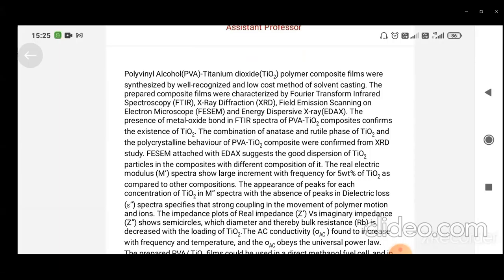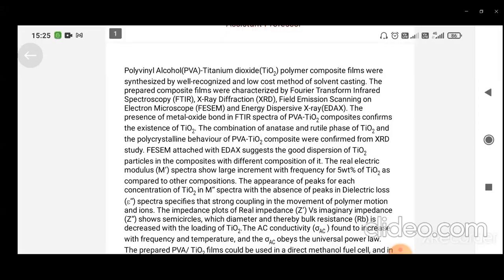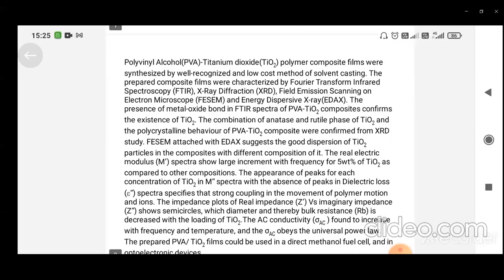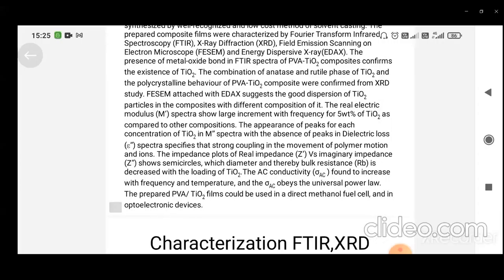TiO2 in polyvinyl alcohol. The polyvinyl alcohol TiO2 composite was synthesized using the solution casting method, also called the isothermal evaporation technique. To begin with, 1 gram of polyvinyl alcohol was added to double distilled water at room temperature and the mixture was stirred on a magnetic stirrer to get a uniform solution. The desired doping percentages of TiO2, 5%, 10%, 20% and 30%, were dissolved in the polyvinyl alcohol solution. The solution was stirred constantly at 50 degrees until it became a homogeneous solution.